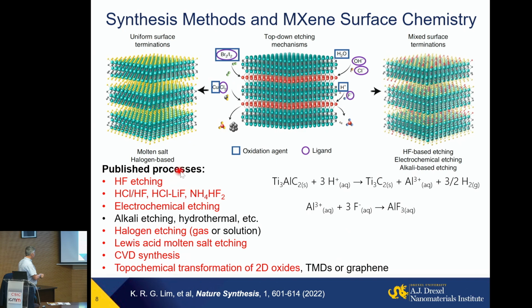We can still use hydrofluoric acid for some of the MXenes, but for many others, we use other fluoride-containing acidic solutions. You can avoid using HF where limited in your lab, for example, using hydrochloric or sulfuric acid with lithium or sodium fluoride, forming some acid in situ. You can use electrochemical etching, another way to control the rate of the process by applying an electrochemical potential.